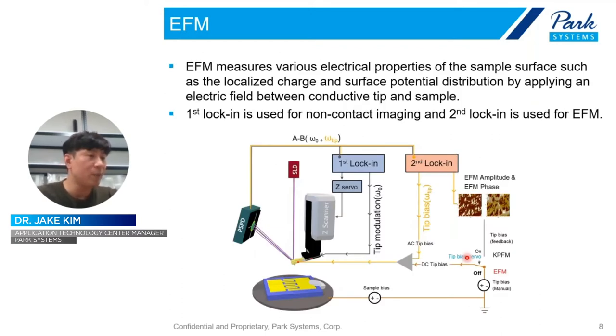And here comes the simple diagram of EFM. Once again, EFM measures the various electrical properties of the sample surface, such as localized charge and surface potential distribution, by applying an electric field between the conductive AFM tip and sample. And to detect the electrical signal, these two lock-in amplifiers are adopted. The first one is for non-contact imaging. And the second one is for the EFM signal. So it means we can obtain both height, like topography, and EFM signal simultaneously.